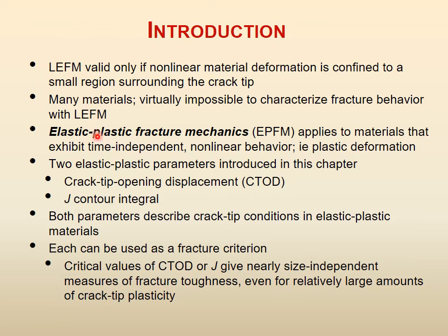So therefore, elastic plastic fracture mechanics applies to materials that exhibit time-independent non-linear behavior. That is plastic deformation, right? Serious plastic deformation, not only in a small area. Now, two elastic plastic parameters are introduced in this chapter. One is called the crack tip opening displacement, CTOD, and the other will be the J contour integral. I will not talk about this now because we will cover it very shortly.